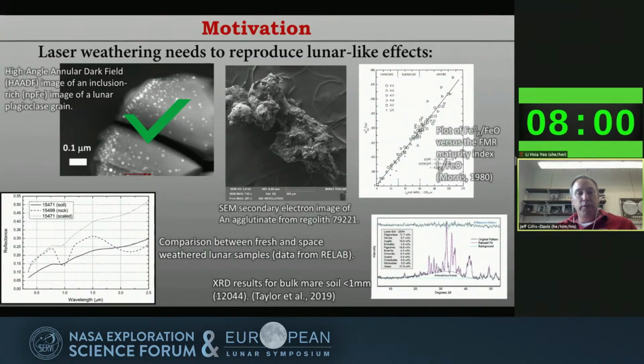Another very common feature in lunar regolith are the agglutinates, which in a mature lunar regolith can comprise up to about 60% modally of the regolith. And with the short pulse only laser, we cannot produce these agglutinates. And by the lack of producing these agglutinates, we also don't make a lot of nanophase iron and microphase iron. And this feeds into the magnetic signature that was measured by Morris in his '76, '78, and '80s papers, where it became a maturity index where the Is normalized to the FeO matches and is used for maturity parameters.